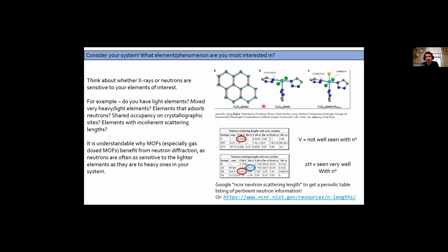And this material itself was a disaster to make. It's like the world's most sensitive MOF. A slight breath and it'll just dissipate, right? So there's a lot of complexity to this whole project in general. But I'll also talk about the spectroscopy perspective. We've said, oh, hydrogen's in it, right? This has a large incoherent cross-section. For diffraction, that can sometimes add to your background. I'll show you an example from my own work. You don't need to deuterate your samples, but know that you need something with a large incoherent scattering length to be doing the spectroscopy on things.